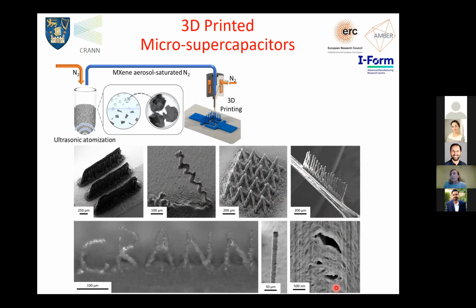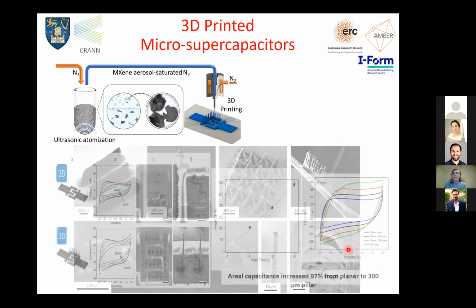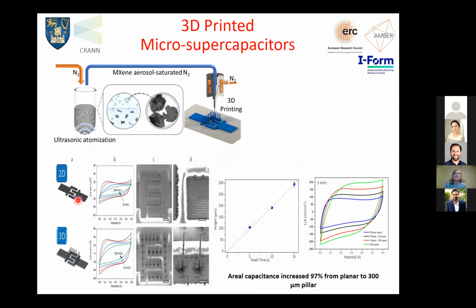Here is a cross-section of one of these devices showing the very, very nice high level of porosity that these 3D printed structures have. And we have compared the performance of 2D printed interdigitated supercaps based on MXene with 3D ones. And again, what we did here was just using the same interdigitated structure, but building pillars. And by simply doing that, we have achieved an areal capacitance that is about 97% higher than planar 2D devices. And this was just literally with 300 micron long pillars.